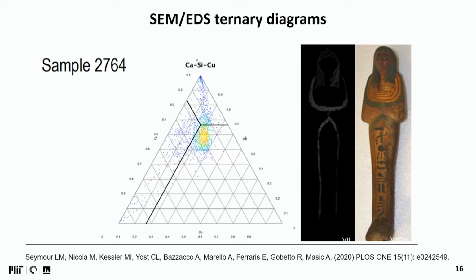Another technique that we applied was SEM-EDS, again plotting these ternary diagrams of calcium, silicon, and copper, perhaps to see differences based on the position of this spot on the ternary diagram. And of course, if you have a different chemical composition, these spots will move.